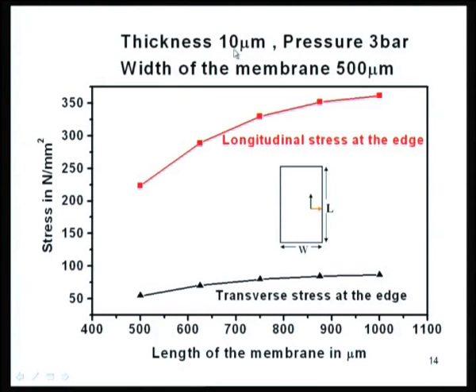For example, this is the simulation using a software called ANSYS. Mechanical engineers use that software. There are other software like Coventorware. W is the width, let us say 500 micron, the membrane is 10 micron thickness, and pressure is 3 bar. If the width is equal to length, 500 microns, the transverse stress at the edge here is about 50 newtons per millimeter square, which is about 500 bar. But the longitudinal stress is about 220 newtons per millimeter square, which is 2200 bar.